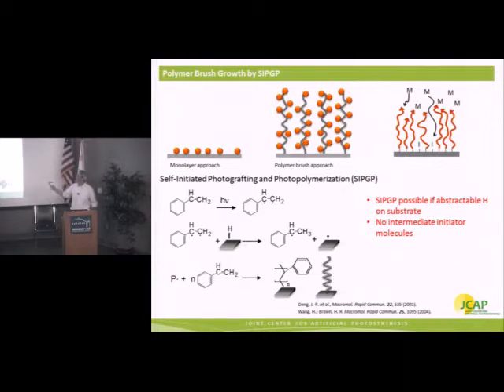So we thought maybe you can utilize the third dimension. We can grow up from the surface. Call it the Manhattan approach, maybe. So instead of being limited, since you can't grow sideways, you can actually expand and achieve a higher loading capacity on the surface if you use a polymer layer, not a self-assembled monolayer.